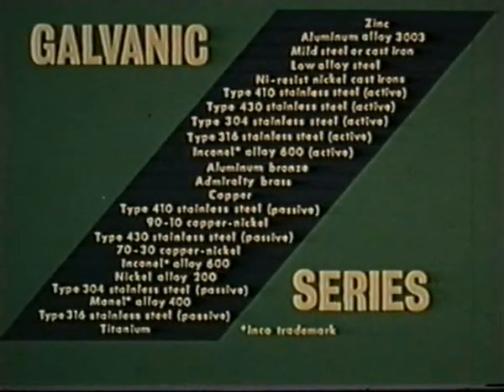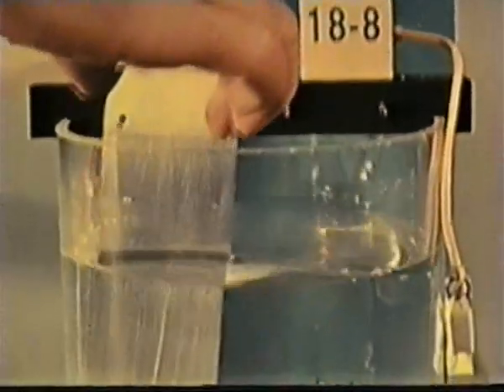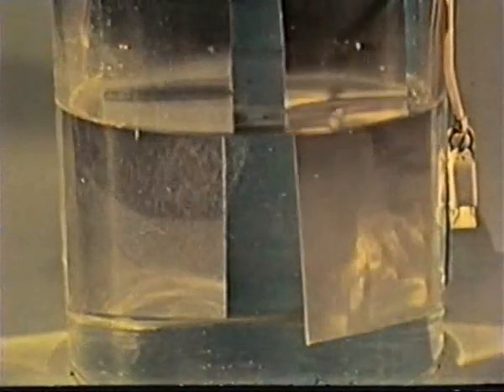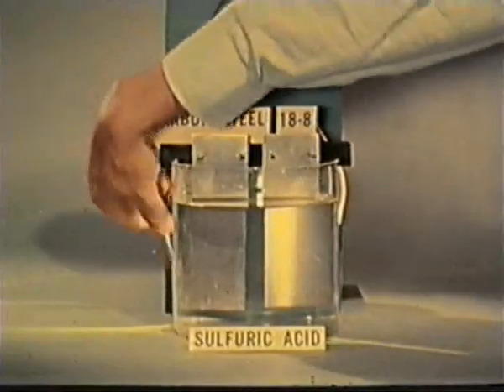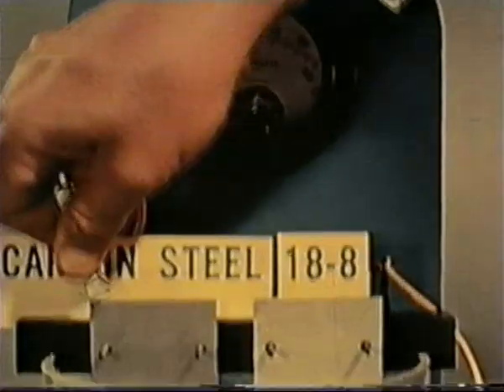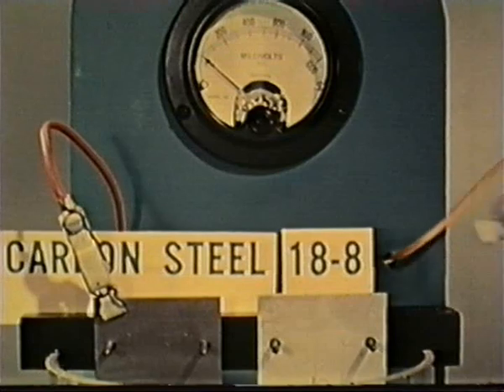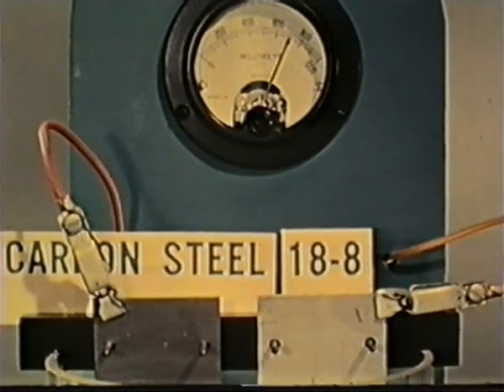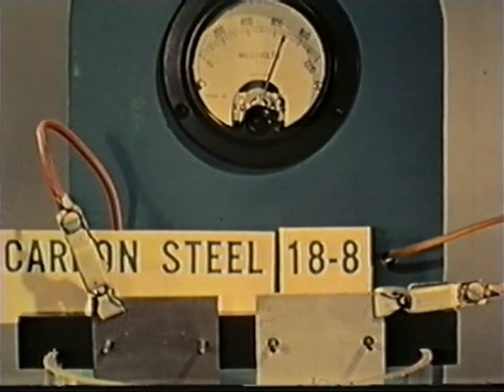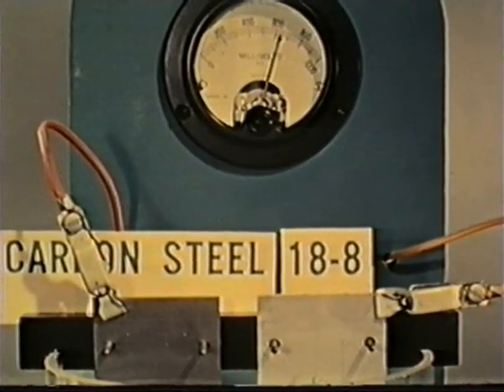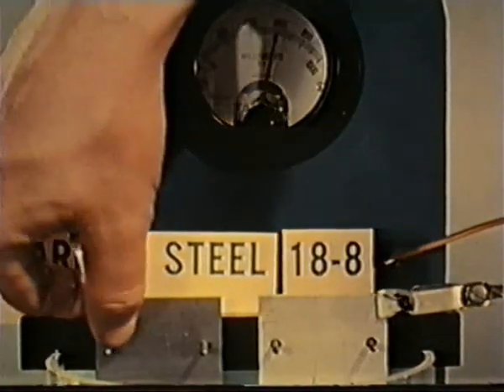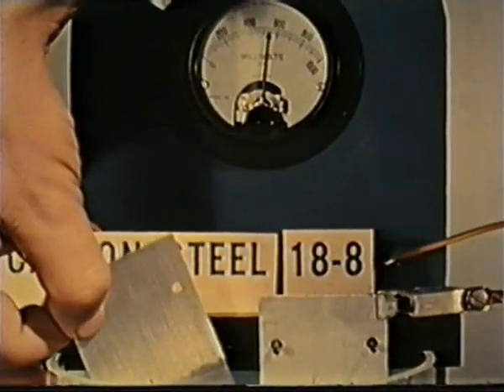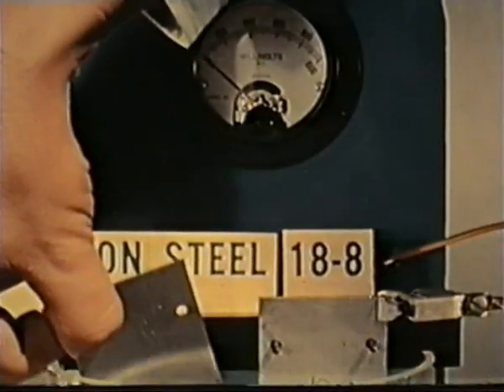And just as happens with iron, the change from activity to passivity also changes the potential of stainless steel. When activated in certain environments, 18-8 stainless steel acts like iron and has about the same potential. For proof, here is a piece of 18-8 stainless steel and a piece of carbon steel immersed in warm sulfuric acid and joined through a millivolt meter to measure their difference in potential. At the start, the stainless steel is passive and shows a potential of 700 millivolts, more noble than the carbon steel. We now bring the carbon steel into direct contact with the stainless steel, so that hydrogen now forms on the stainless steel surface and destroys the film responsible for its passivity and its noble potential.